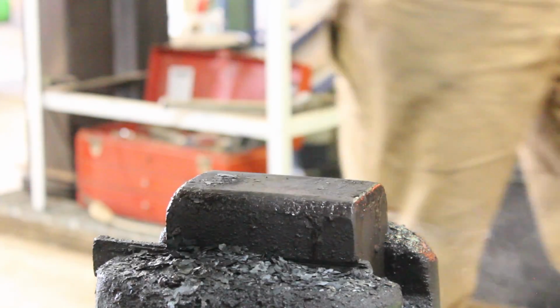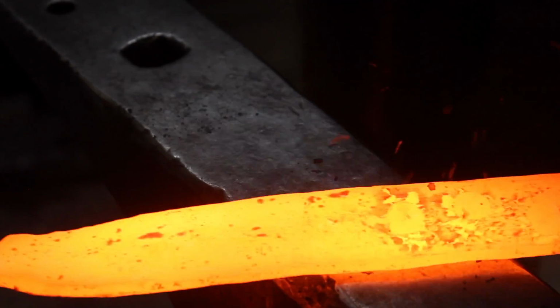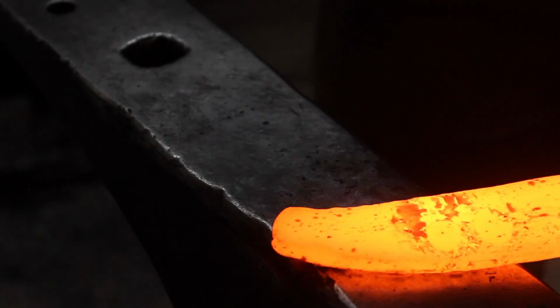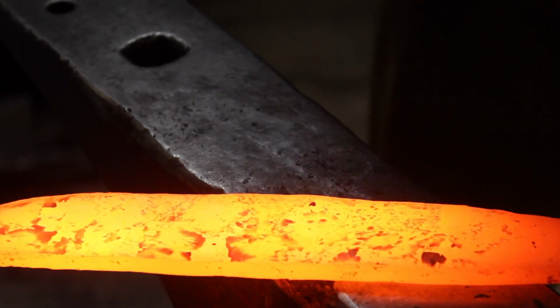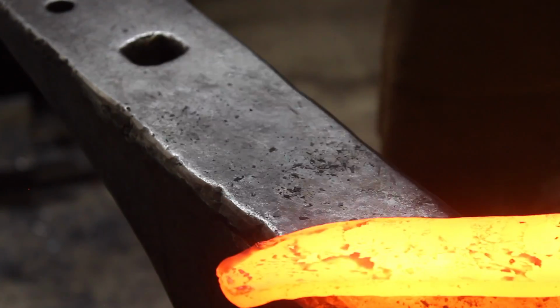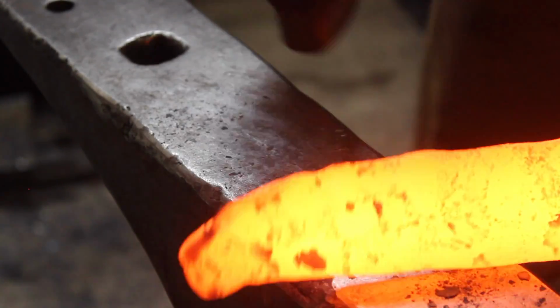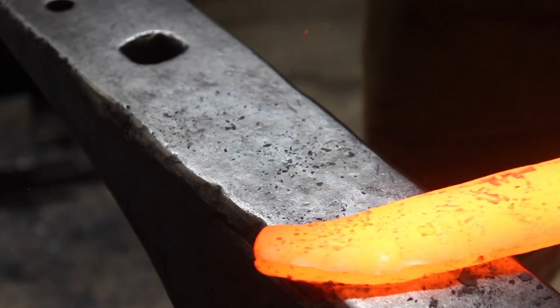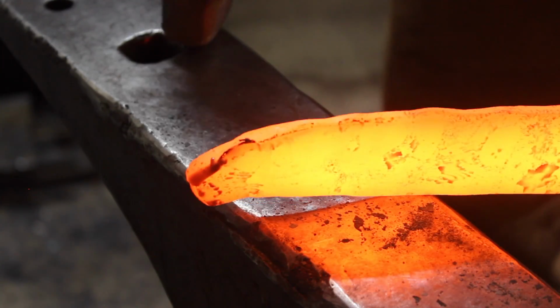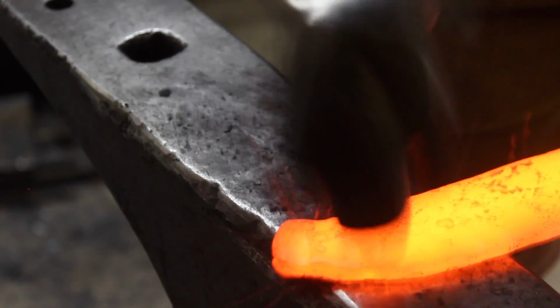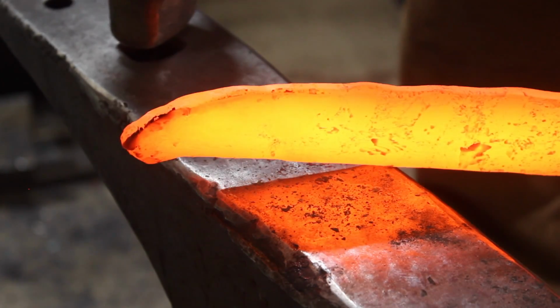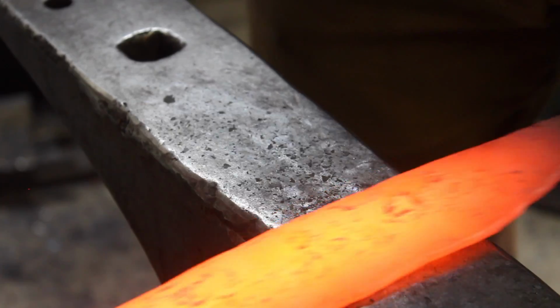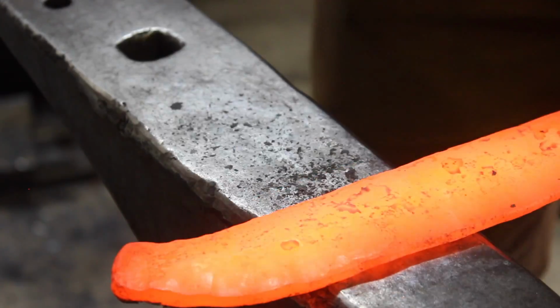Here, as we near the finished forge dimensions, we're still at about a 1/4 inch thick on the edge here. And I'm using my straight peen hammer to forge in wavy lines, for lack of a better term, and that's going to create more of a pattern in the Damascus cladding on the finished blade.